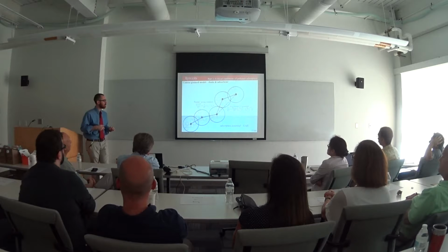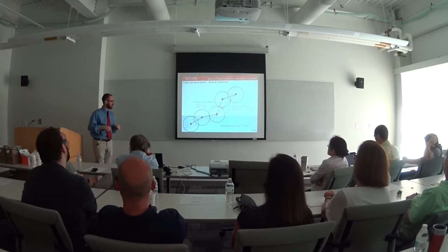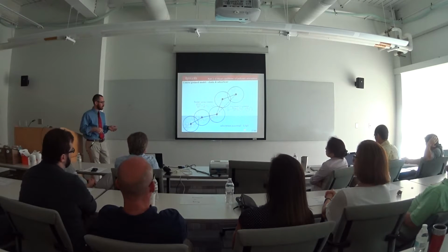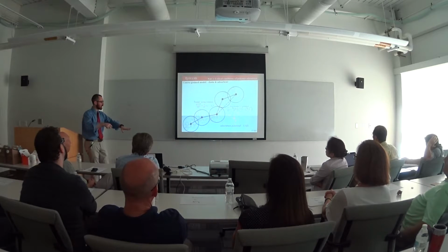In all of this section of the work, I use the same coarse-grained model. Our beads, which are shown in the black circles here, are represented by Lennard-Jones spheres, which are connected by harmonic bonds. And beads which are not directly adjacent to one another interact via a Lennard-Jones potential. In all of my modeling, I do not include an explicit solvent. And so in order to account for the adsorption interactions with the surface, I have to introduce an adsorption potential along the surface. For simplicity, we use just a simple square well. Our adsorption potential is called U.